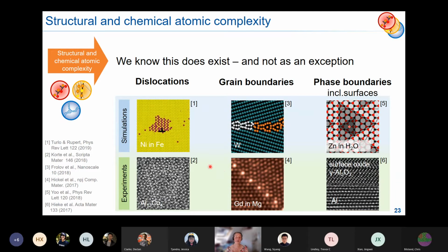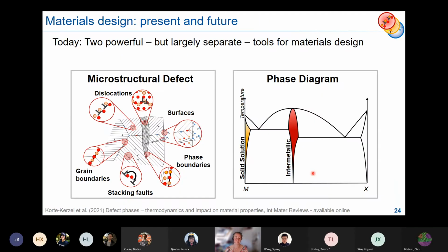The chemistry changes and then the structure changes as well. There must be driving forces for that to happen. It can be at dislocations, it can be at grain boundaries. You can also have phase boundaries, and that will include surfaces where you find distinct structures coming up. So they also must have a thermodynamic stability that has a driving force for this to happen.